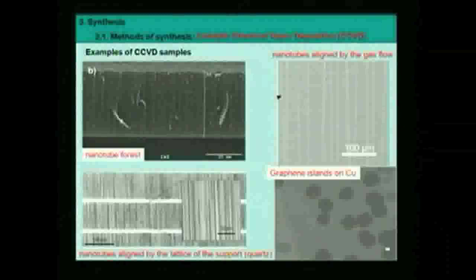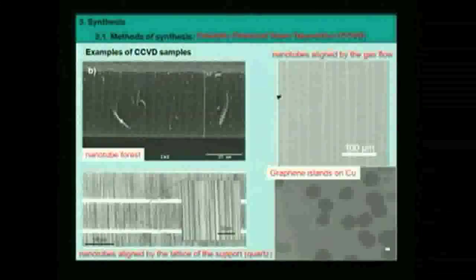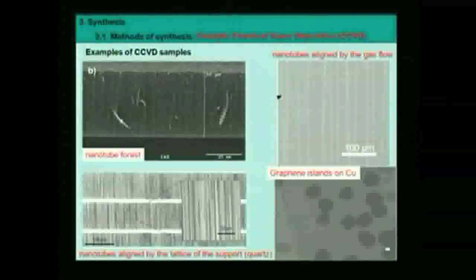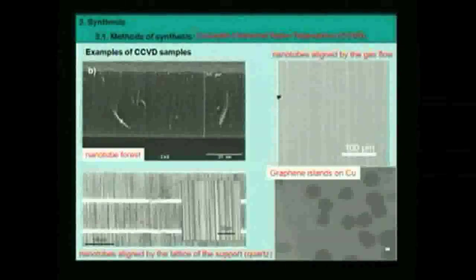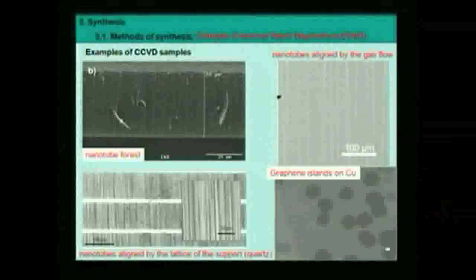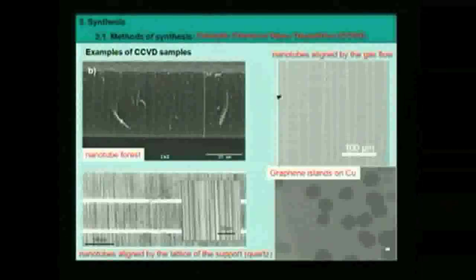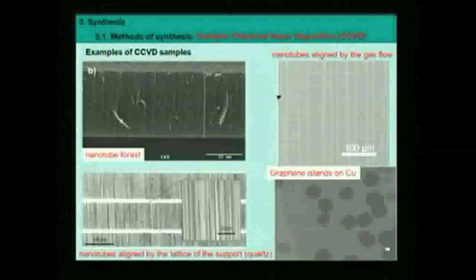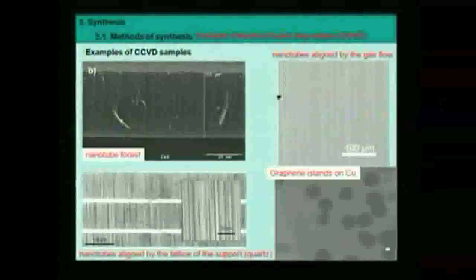Another question. In this kind of synthesis, do you have catalyst remaining after you obtain the carbon nanotube? What do you do with that? About the purity of the carbon nanotube. Okay, so this is an important problem, to remove the catalyst after the growth. I do not plan to talk a lot about that, but there are different techniques to get rid of the catalyst after the growth. For instance, you can use acid treatment. Many acids can selectively remove metals like nickel, iron, cobalt without destroying too much carbon structures. Okay? This is the main way actually to get rid of the catalyst.